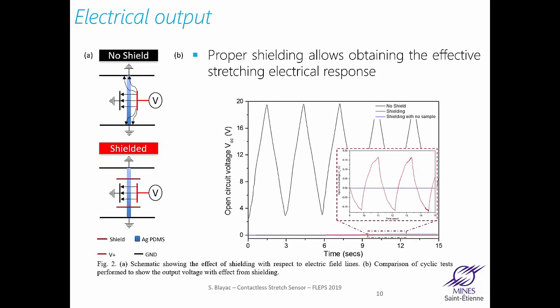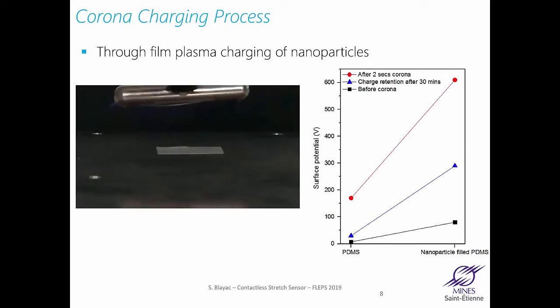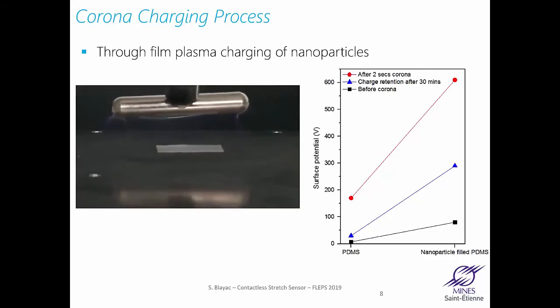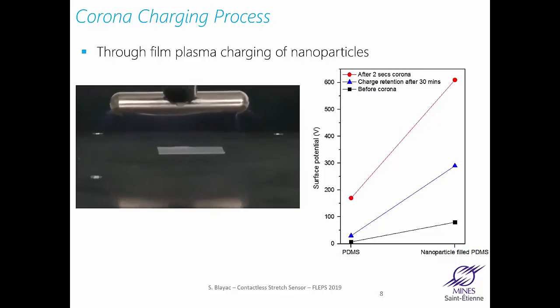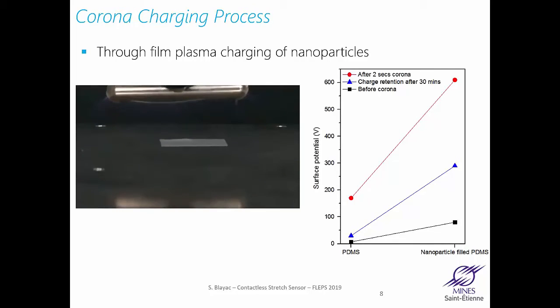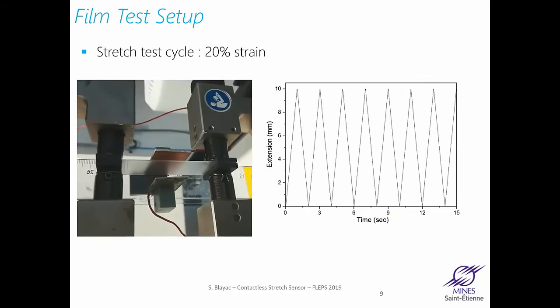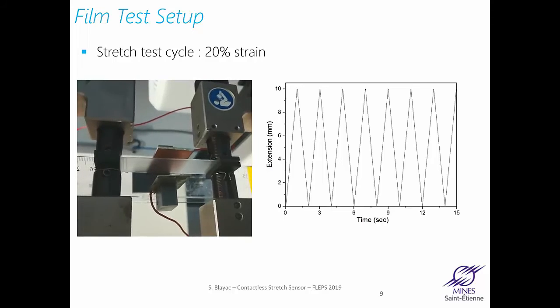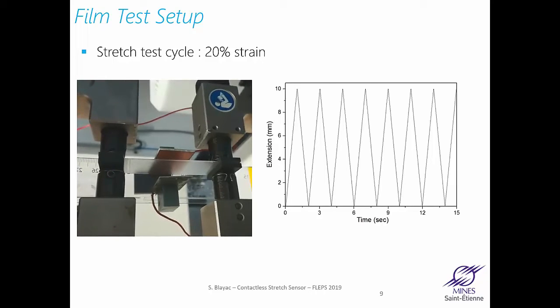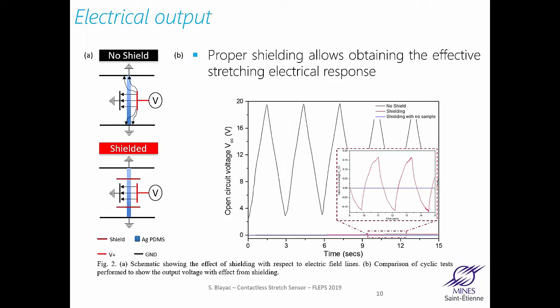Once it is done, sorry, the video should start now. Once it is done, now we just have to charge it by corona effect. And we obtain some charged films that are ready to be used for test. We then put it in a stretching machine, and we obtain this kind of variation of position. And we study the electrical response of this film by just looking at the voltage that we have between the two electrodes, this with contactless configuration. So what we obtain, if we do this, we obtain this response in terms of electrical parameters, but this response is